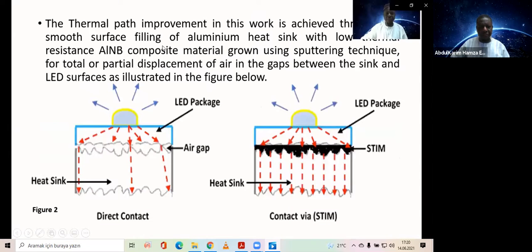Now, the thermal path improvement in this work is achieved through the smooth surface filling of the aluminum heat sink with a low thermal resistance aluminum nitride boron composite grown using the sputtering technique for total or partial displacement of air in the gaps between the heatsink and the LED surface, as illustrated in the figures below.